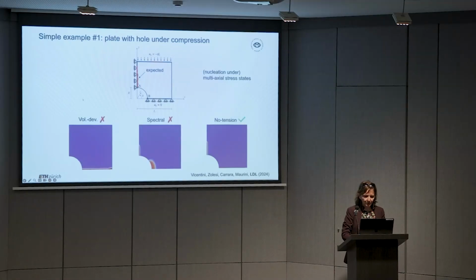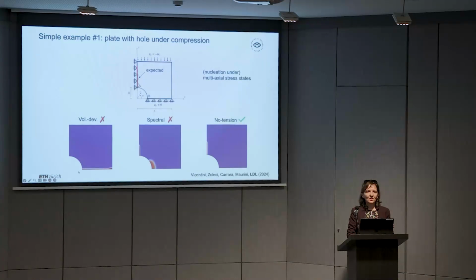So if you use the most famous energy decompositions, the volumetric deviatoric will give you completely wrong results. You will nucleate at the point that is under compression, and the crack will propagate horizontally. If you use the spectral decomposition, you start nucleating some homogeneous damage, some smeared damage in the wrong place, and in a second stage you will start nucleating a crack in the right position. So still not satisfactory. And if you use another decomposition that is due to Freddi and Royer-Carfagni, the so-called no-tension model, then you get a good behavior. And then you would think, okay, let's all use the no-tension decomposition. That's a good one. Yeah, but let me show you another example.